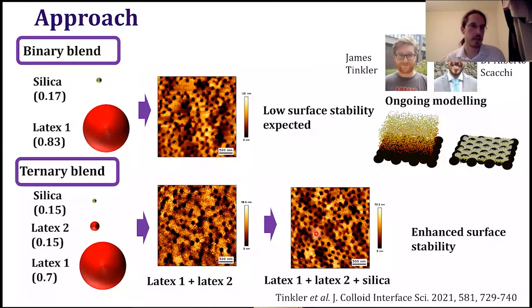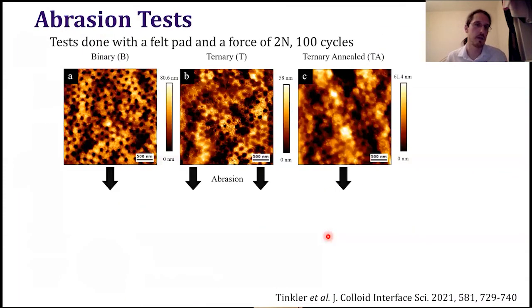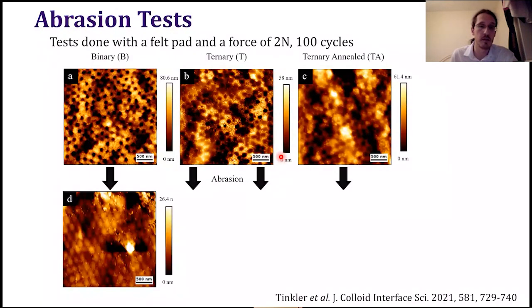we did the abrasion tests on the different ones. So we have the binary, just the latex with the silica on top. If you abrade that for a while, with 100 cycles using a felt pad, so it's not really hard abrasion, but it's some kind of wear on the surface, you can see that after doing that, you basically remove all the silica. You see the very round features, which are just the latex particles, and all the silica that was at the top is gone.